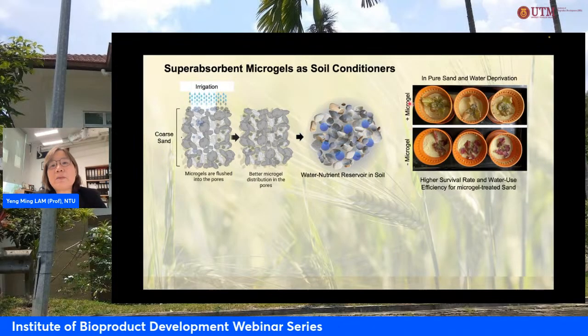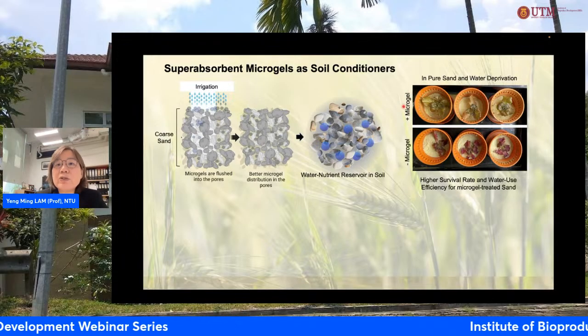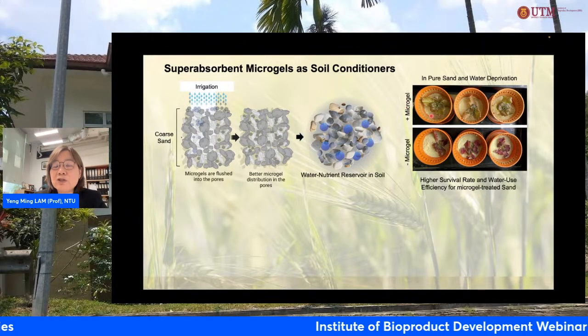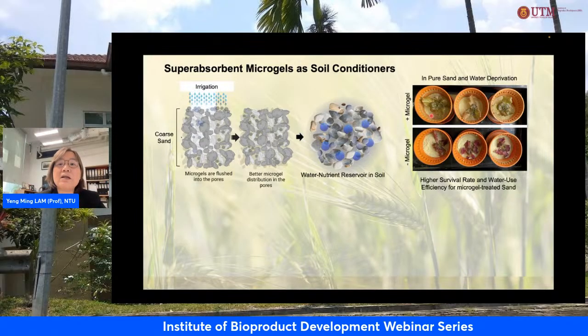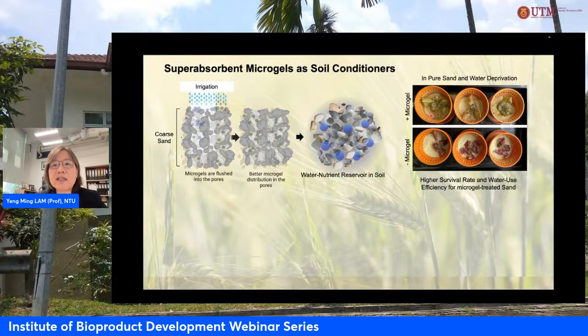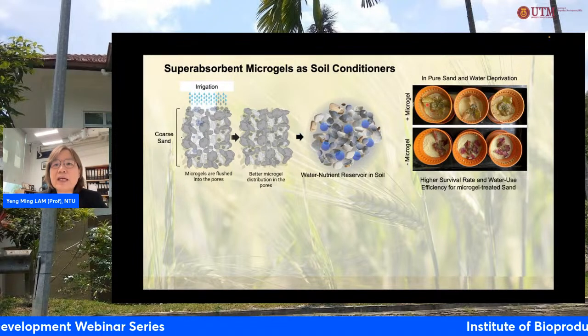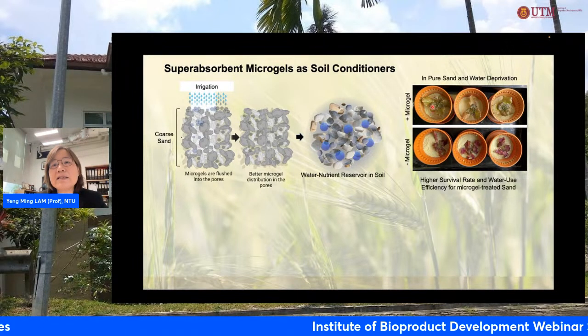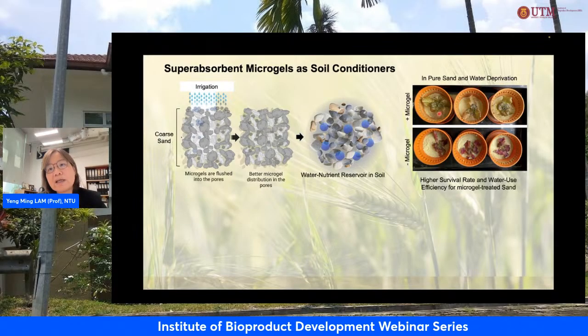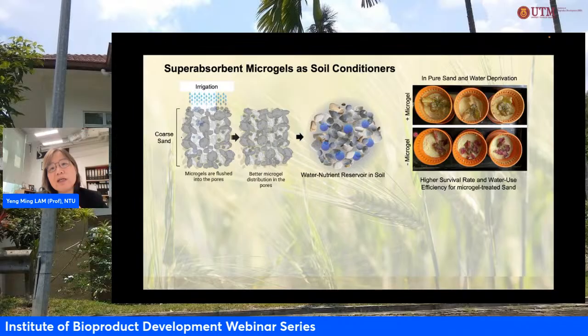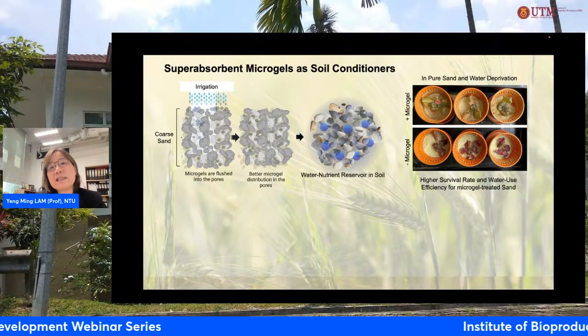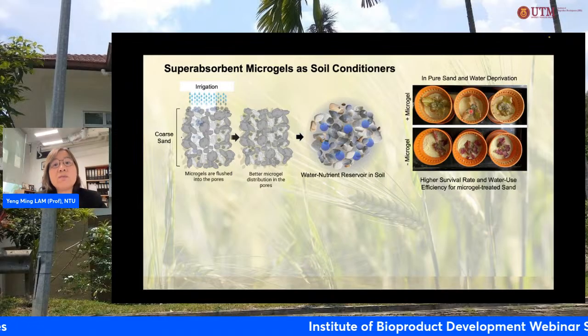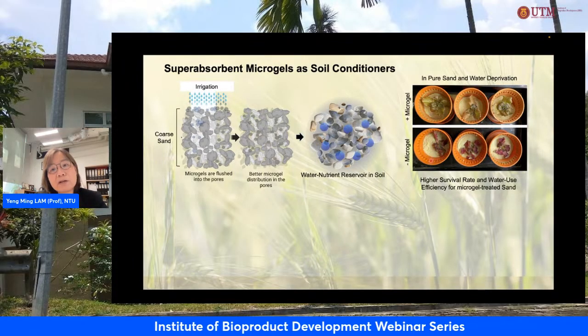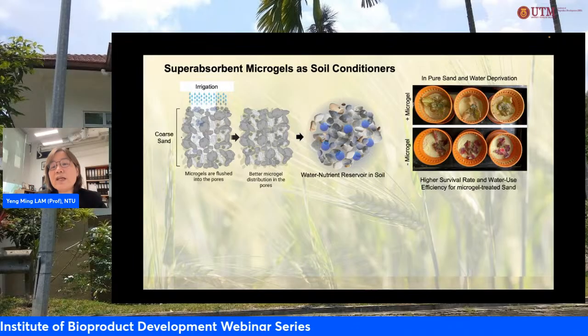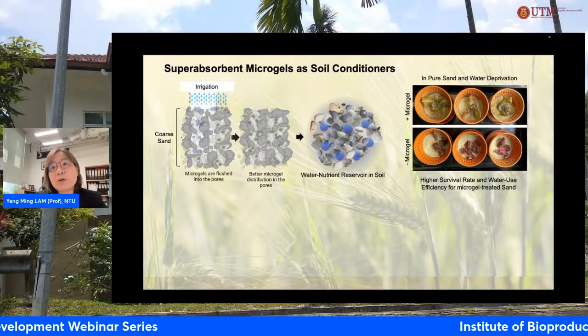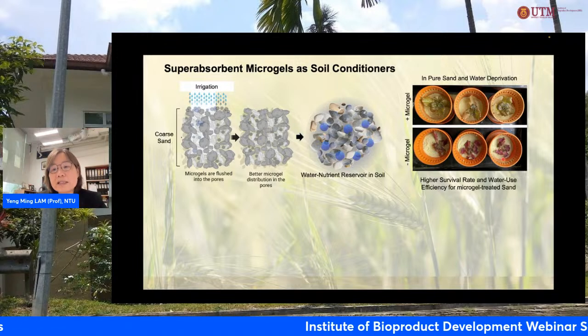And if you look at this example, this is with microgel, with our Retensil G in pure sand. This is sand. We try to push it to the extreme condition, which is the sand used for your aquarium, which is very, very clean sand. No nutrients, nothing. So with this sand, we can now plant even lettuces. These lettuces will express stress. So when there's water stress, it will turn purple. This one is with microgel. This one is without microgel. With microgel, you can see that the leaves remain green, and it remains very supple. And without any microgel, it's just water. Over time, the plant starts to express signs of stress. That's the reason why it turned purple.